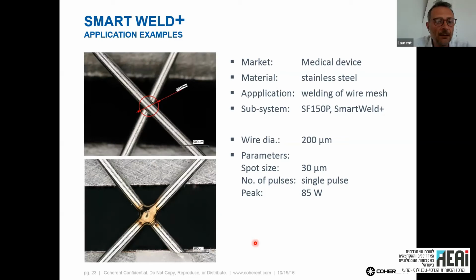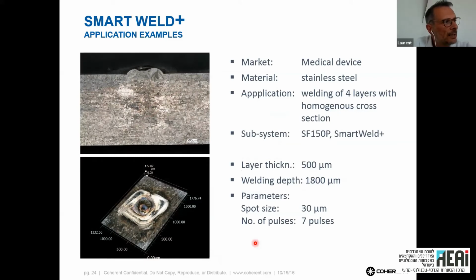This is a good example of what one pattern allows, with, again, a very good beam quality and a very small spot size, 30 micron. This is what we are able to do. It's difficult to see on this picture, so I hope you will trust me. It's a weld, but with 4 layers. You have one layer here, another one here, here, and here, all of them 500 microns. Of course, in this case, you should imagine a clamping device to clamp all the layers, to be sure that we will not have any gap. But this gives you an idea about what we are able to do. Again, 30 micron spot size.